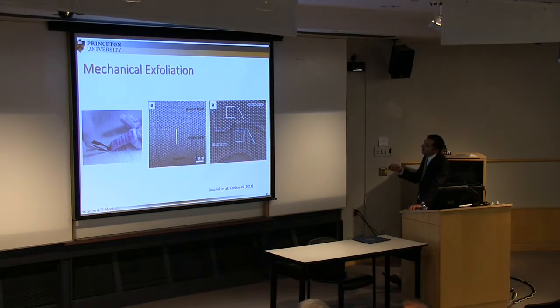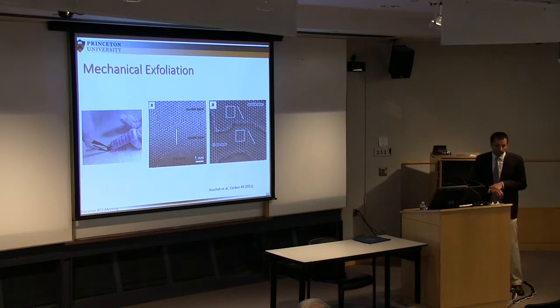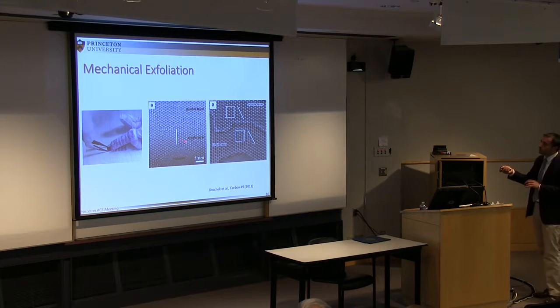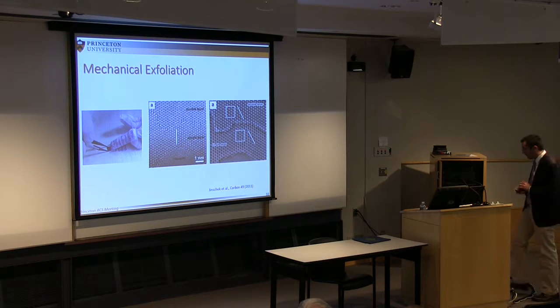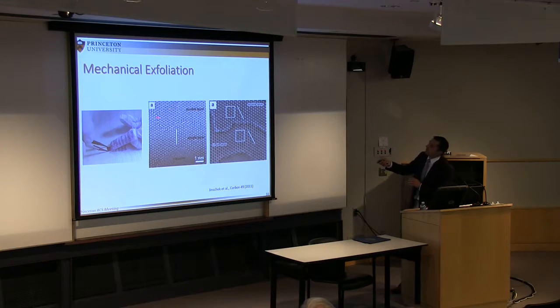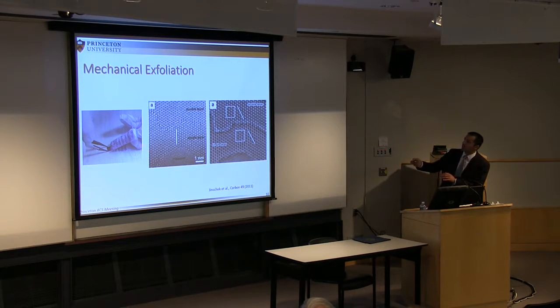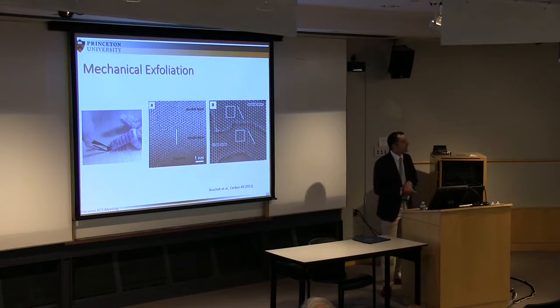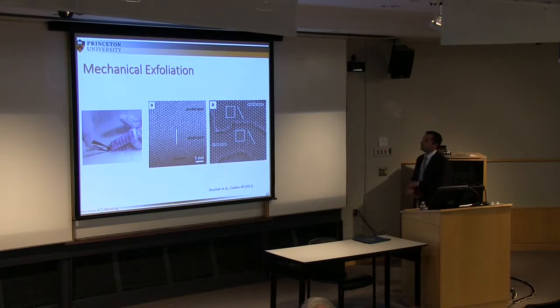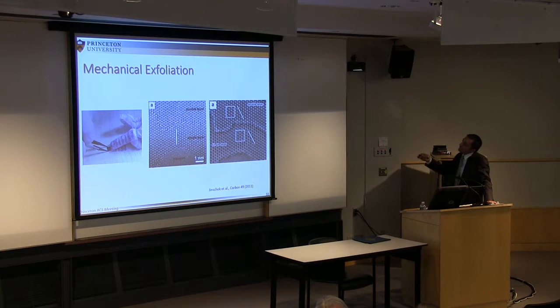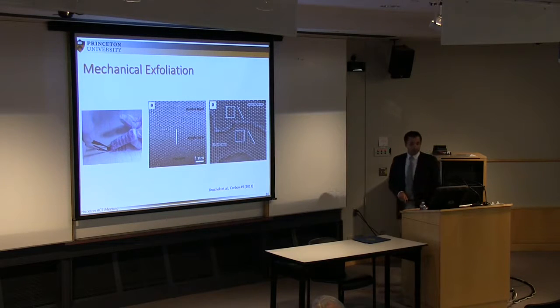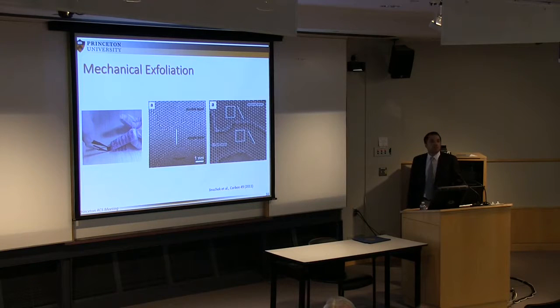And here you have transmission electron microscope images. The one on the left is the image acquired as it is on a high resolution TEM. You have the graphene layer starting here. You can kind of guess the honeycomb structure already. And then you have a second layer here on top of the first one, so you can see a contrast at the boundary between the two. And with recently very powerful TEMs, now with several lenses to correct for aberrations, astigmatism, etc., you can even get images like that. This image has also been processed further with Fourier transform, etc. If you remove the background noise, you can resolve now the individual atoms. And at the university here, we also have a microscope that can do this type of imaging now.